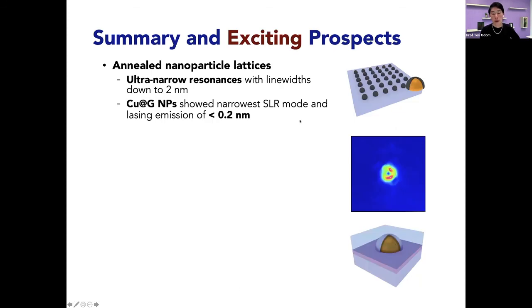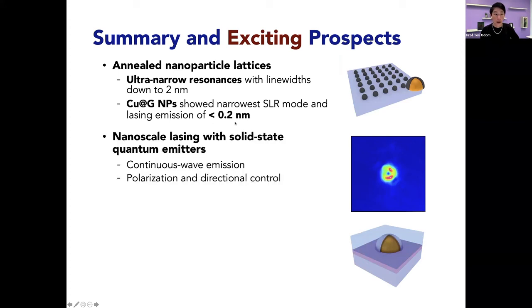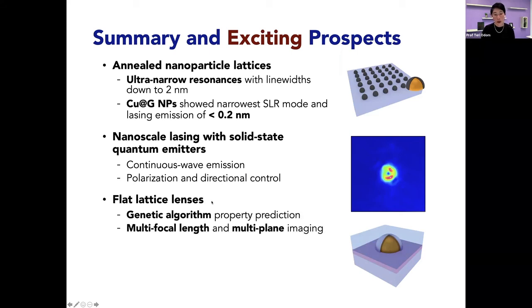Okay, so in summary, I've tried to introduce this nanoparticle platform where you can do chemistry, you can anneal them to achieve narrower resonances, and then if your plasmonic material is catalytic, you can even grow things like graphene. I introduced nanoscale lasing with the solid state quantum emitters. We're able to achieve continuous wave emission as well as polarization and directional control.